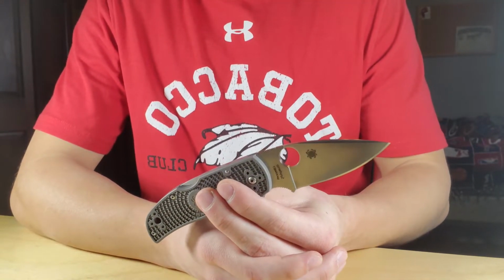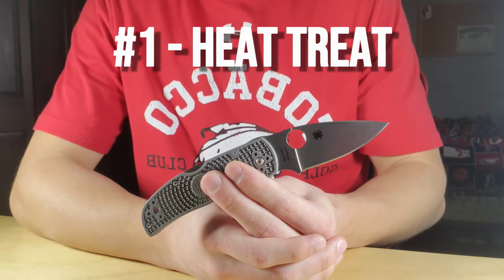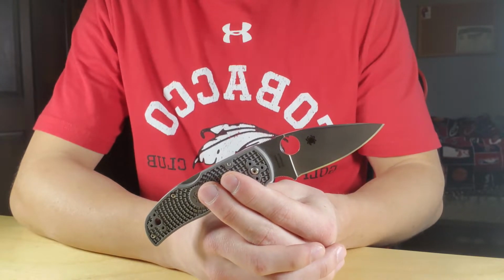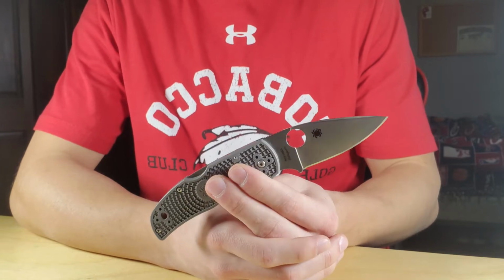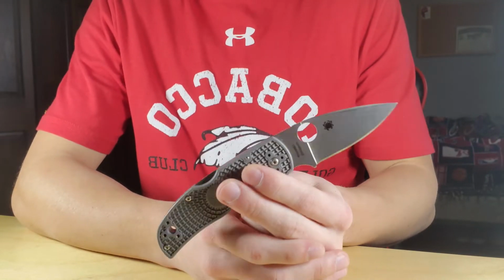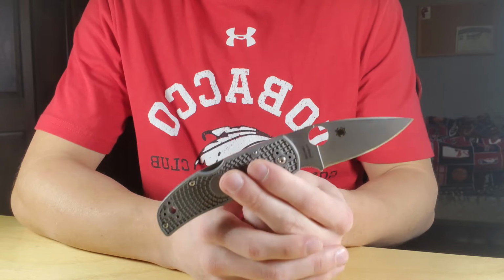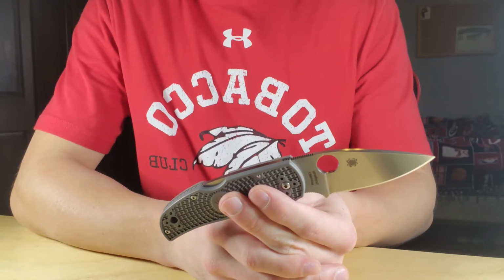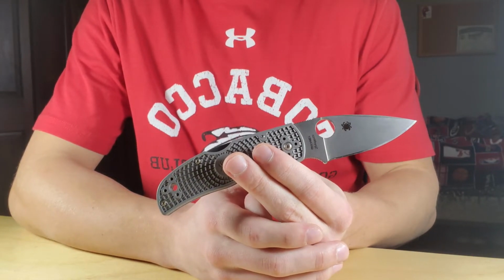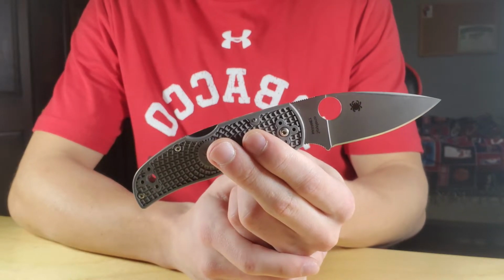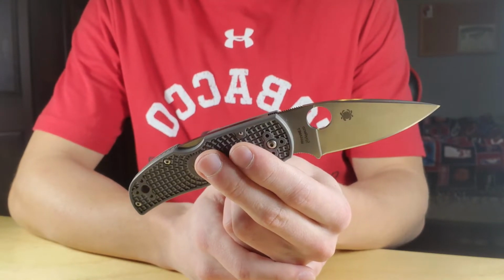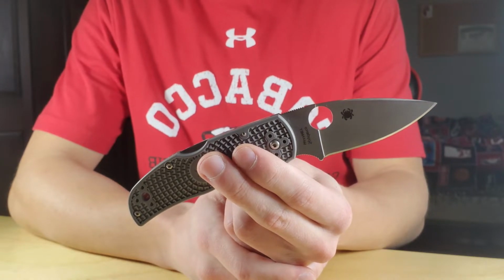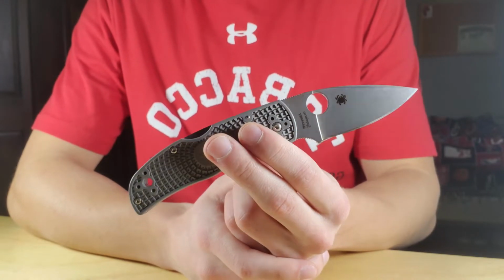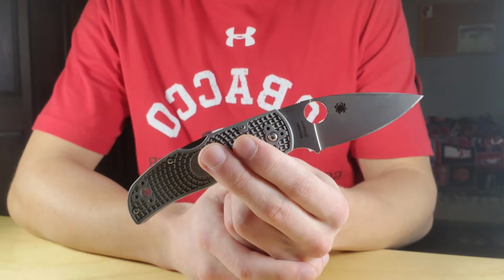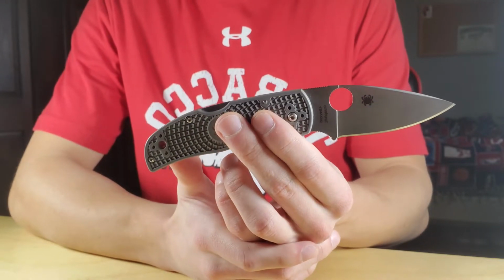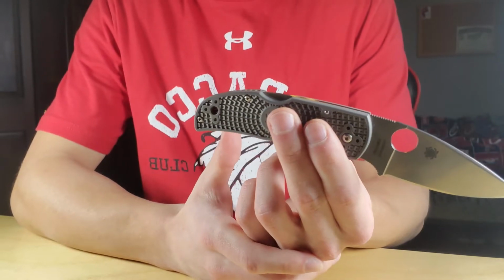And first and foremost, we have heat treat. This is the most important factor of performance, and it's not really even close. Heat treat makes or breaks a knife. Let's give an example real quick. I know that Steve had a Maxamet Manix, and his came in at like 66 HRC or something, and it performs nowhere close to what this one at 69.2 does. Same steel, same composition, but the specs for the heat treat were different on his batch compared to this batch, and this batch obviously is going to cut longer because it's harder, like we talked about in the last point.